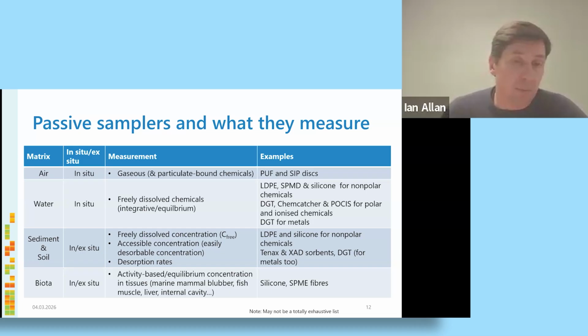The deployments are mostly in situ, and that's the same for water, measuring freely dissolved chemicals in water. When we're looking at non-polar, non-ionized chemicals, we're using low-density polyethylene, SPMDs, which are LDPE with triolein lipids inside, and then silicone membrane. The DGT, ChemCatcher and POCIS devices have been developed and used mainly for relatively more polar chemicals and ionized ones as well.